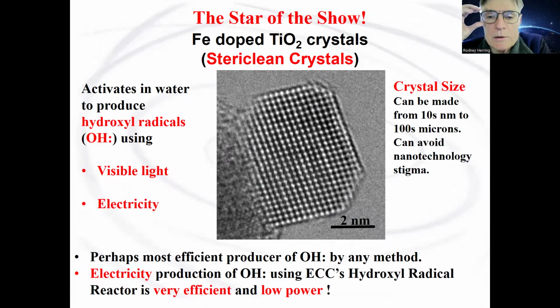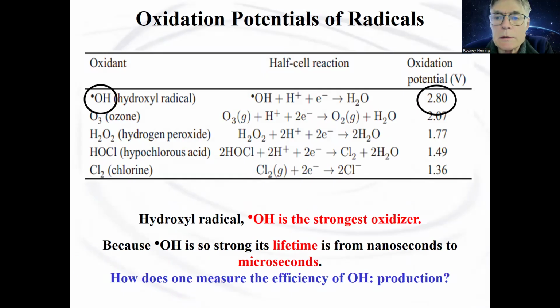So this is an example of the crystal produced, iron doped titanium dioxide, and it can be activated using visible light or electricity to produce hydroxyl radicals. The size can be adjusted from tens of nanometers to 100 microns, so avoids that nanotechnology stigma. Perhaps this crystal here is the most efficient producer of hydroxyl radicals by any means. We have an electricity generated reactor generating these hydroxyl radicals, and you'll see that it's very, very efficient and low power. And why do we want hydroxyl radicals? Because they have the highest oxidation potential. It's so strong that the lifetime of this radical is from nanoseconds to microseconds.